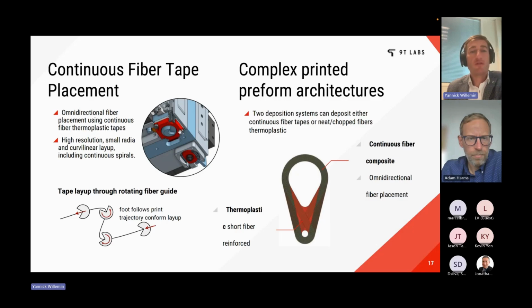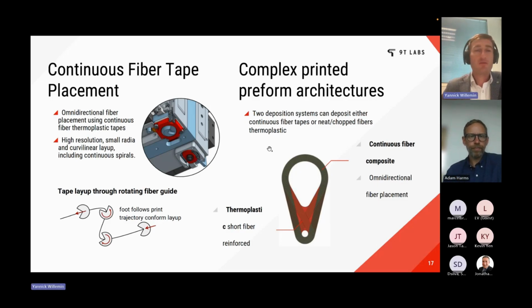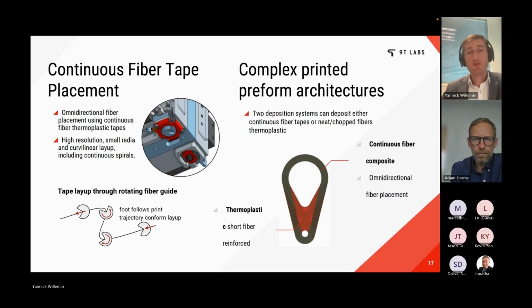And the way we developed this deposition foot is such that we can even rotate this deposition feed and therefore avoid any fiber distortion in the tight angles or around holes. And on the other deposition foot, we are bringing a pretty classic 3D printing filament, either neat or short fiber reinforced, so that we can mix, as you see on the drawing at the bottom right. We have some strands of continuous fiber going around the holes in a kind of H shape, and the remaining material is here printed in short fiber reinforced plastic. Of course, both polymers need to be compatible.